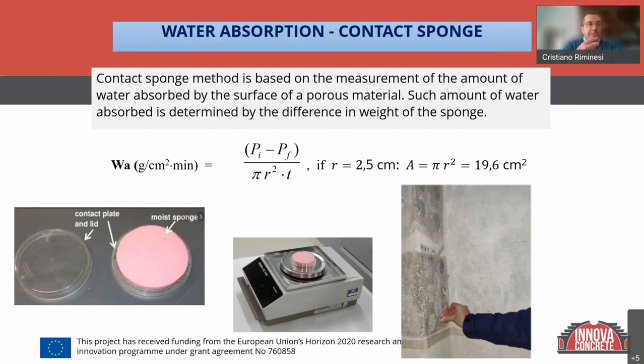The quantity of water inside the sponge is transferred into the substrate. So the difference in weight between before and after the application on the surface allows us to understand how much water the surface has absorbed. In the case of a perfect protective product, the same weight would be found before and after the application.